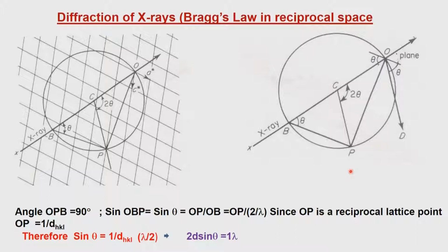from a plane. So what is happening is now the X-rays are coming in, and let us say we have a crystal here. The crystal is consisting of a large number of planes, and one of the planes is shown here which satisfies the Bragg condition. So once it satisfies the Bragg condition, it will generate an H vector in the direction OP. So we have therefore a scattering direction OP, which is now the reciprocal lattice vector. So this is with respect to O as the origin.